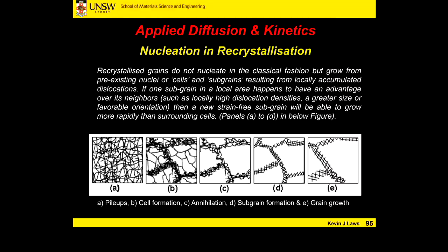Often, at a grain boundary or the corner of a grain, the intercept of multiple grains, we can form cells of dislocations. This might be a specific crystallographic orientation where we're forming a high concentration of these dislocations. When dislocations come across one another, they can get tangled within each other. They hit a grain boundary, they stop, then another one piles up behind it. It's just like a big traffic jam in there.